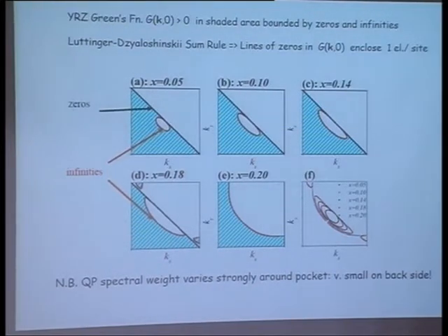So this form here is fixed because we've kept this divergence fixed. And what we find is when we introduce some holes, the holes go into this nodal region because, of course, this is the form where our d-wave form for the RVB gap vanishes exactly along this nodal region. So these pockets then expand, and finally, when this RVB magnitude of the gap is small, you get a small region with an additional electron pocket, and these coalesce, and you get back to the full Fermi surface.